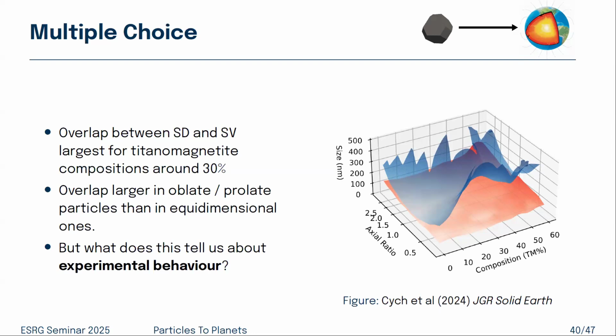We don't know how relatively stable those states are. It could be the case that in some of this region, that single domain state is stable, but far less stable than the single vortex state. And therefore, realistically, you only have the single vortex state energetically, right? So we really need to start digging into how the energy landscape, like those surfaces that I showed you before, look for these things.